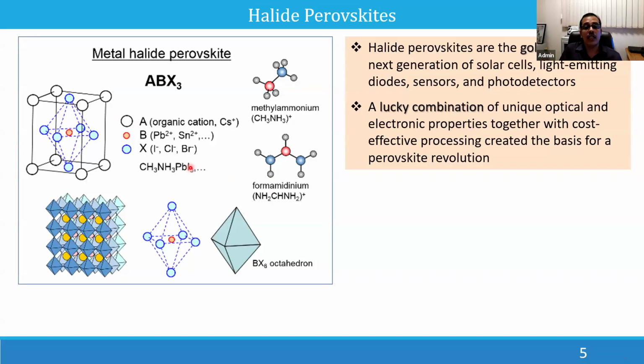The only difference is in the last component: instead of oxygen, it is a halide anion. And mostly people started using organic cations instead of inorganic cations, like methyl ammonium and formamidinium cations. These are very small organic cations. Of course, you can use inorganic cations also, and you can produce all-inorganic perovskite. If you are using an organic cation like methyl ammonium or formamidinium, you will end up with a hybrid perovskite. That is the organic-inorganic halide perovskite, or it can be called hybrid perovskite.